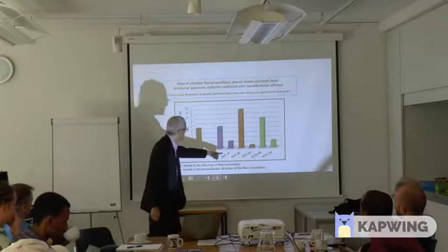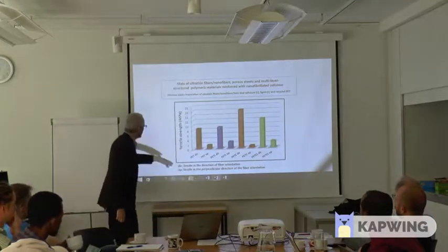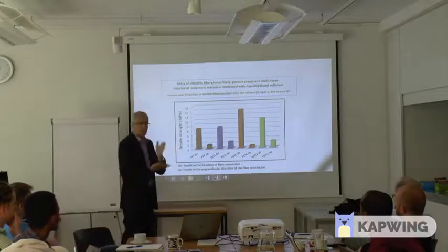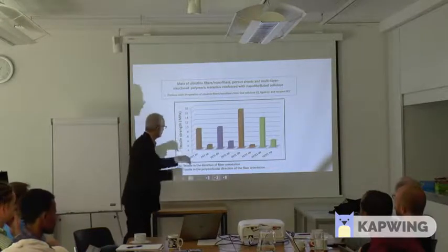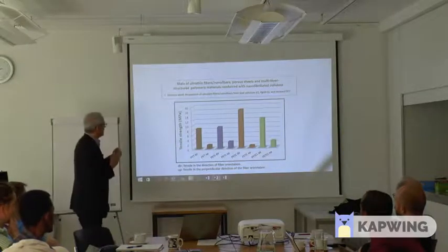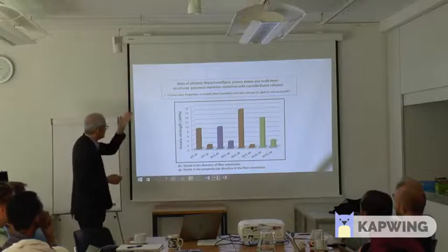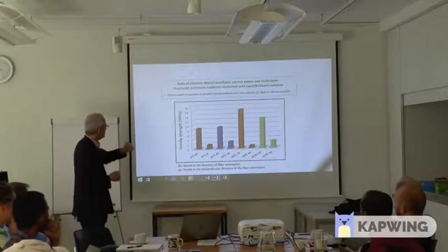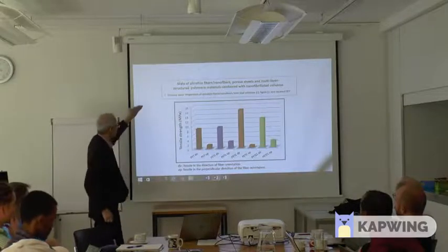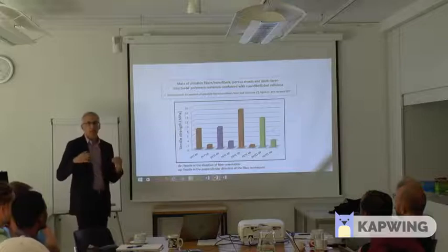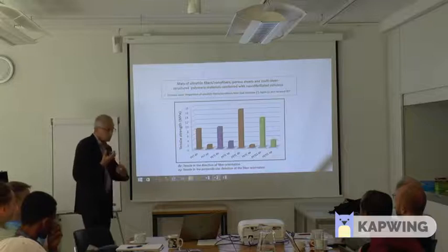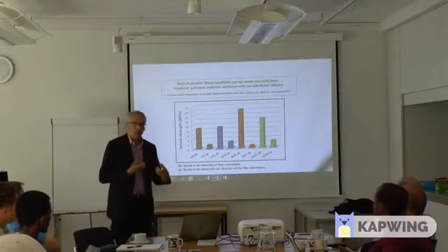Comparing to PET in the preferential alignment or in the perpendicular alignment, we see that, of course, in the direction of the fibers this can be very helpful, even doubling the tensile strength. So those natural resources can improve the mechanical performance.